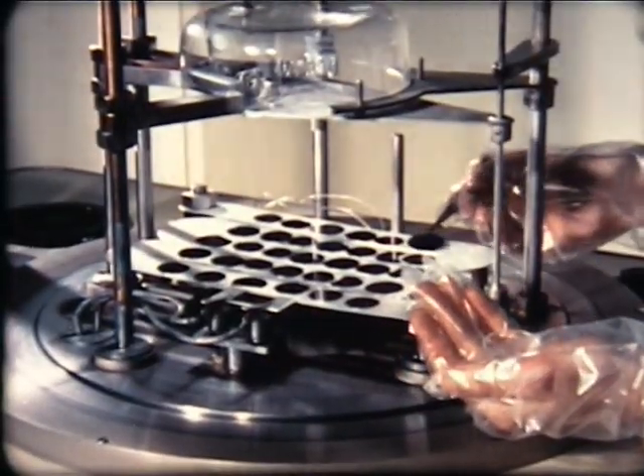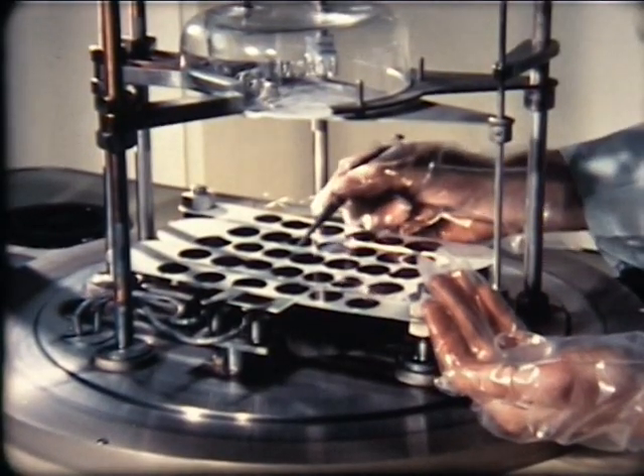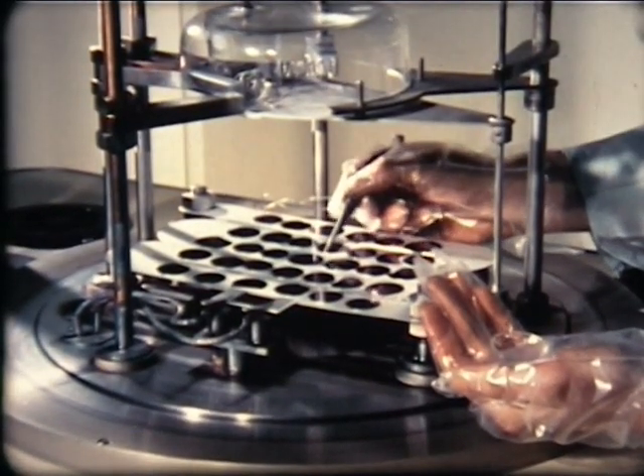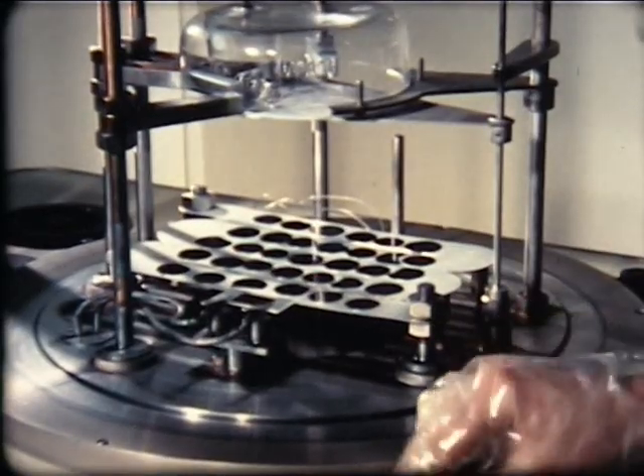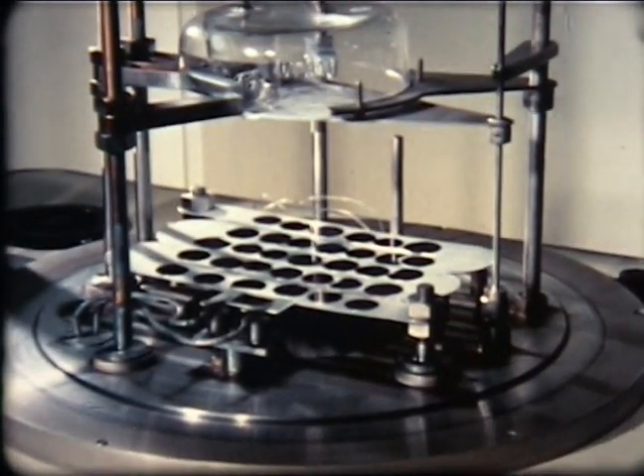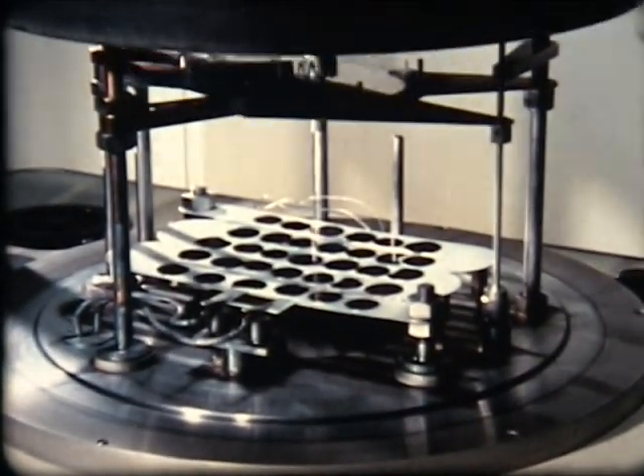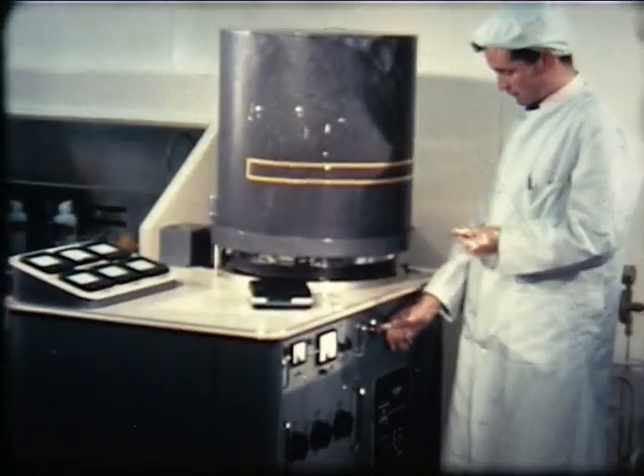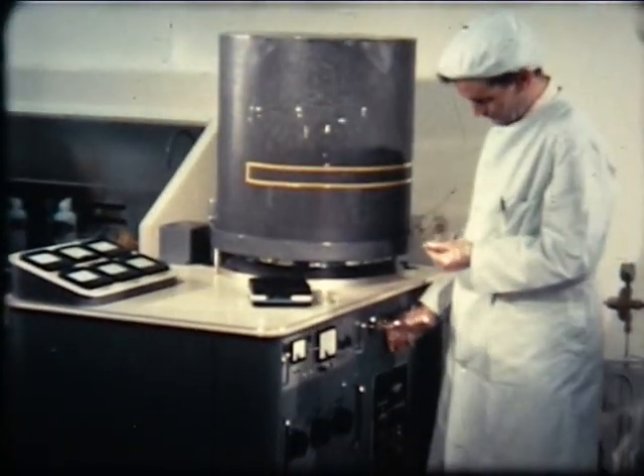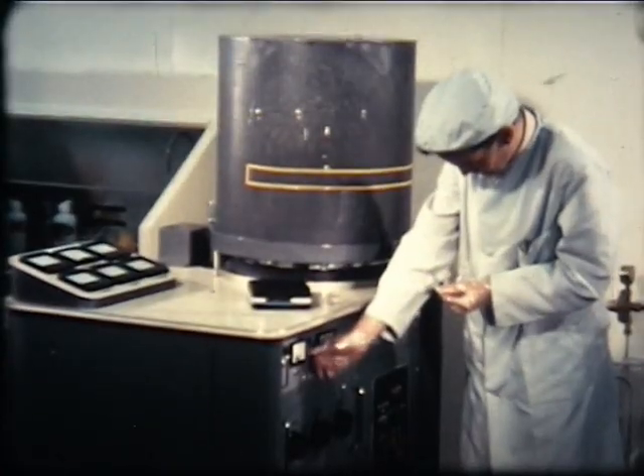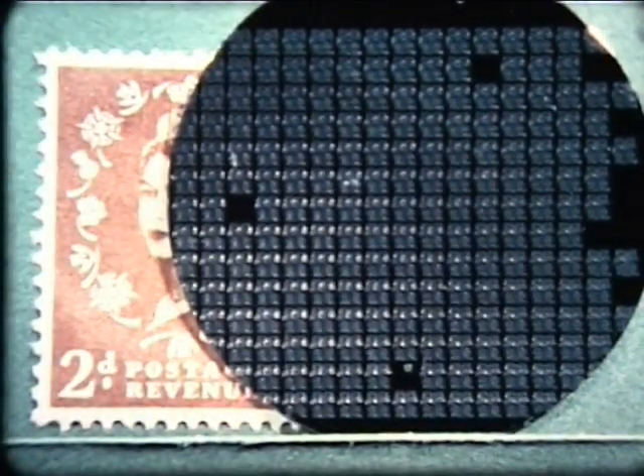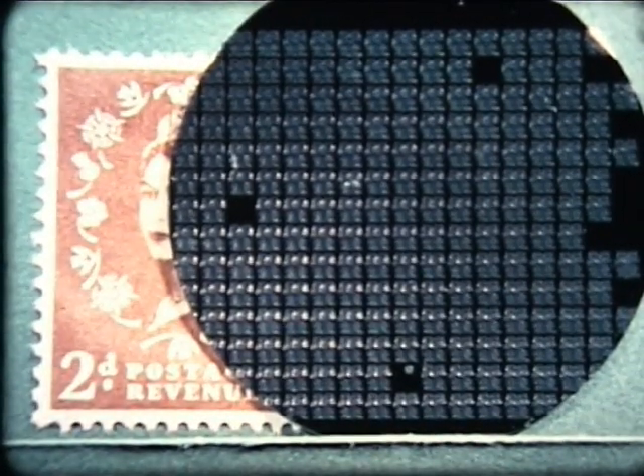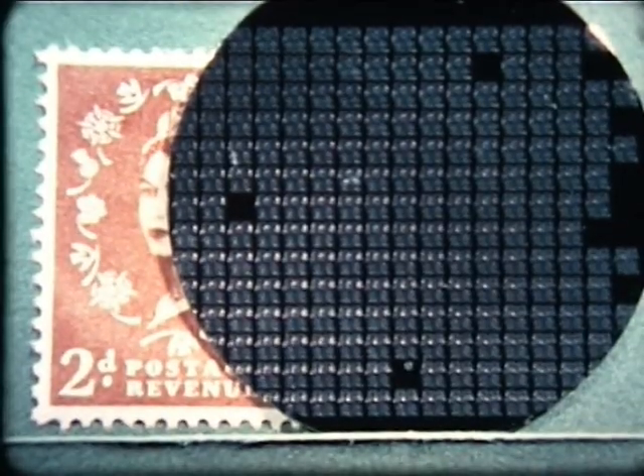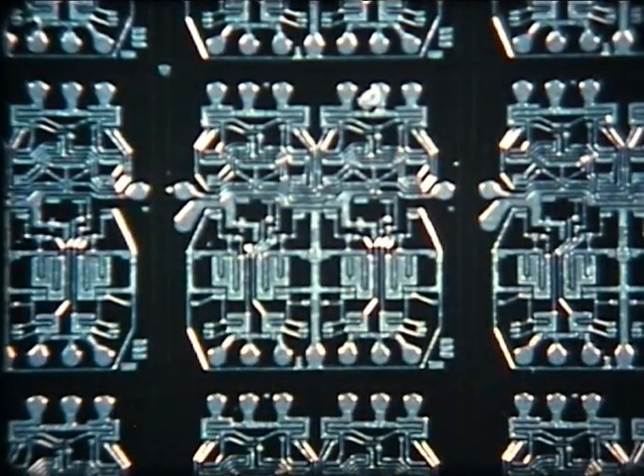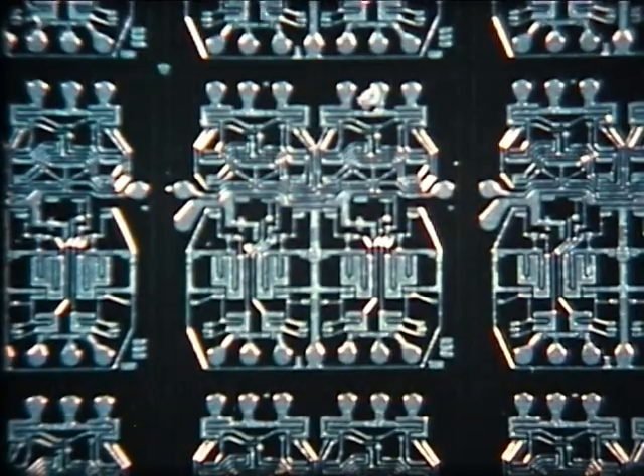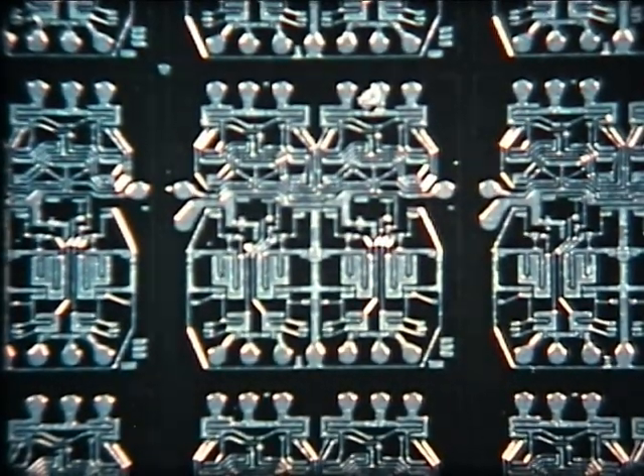The remaining interconnections and input and output connection points are formed by evaporating aluminium onto the surface. Afterwards, unwanted aluminium is removed by a final mask printing and chemical treatment. The slices are then complete. A slice is about 32 millimeters in diameter. It contains several hundred circuits, each about 1 millimeter square. Each circuit may contain 100 or even more components.